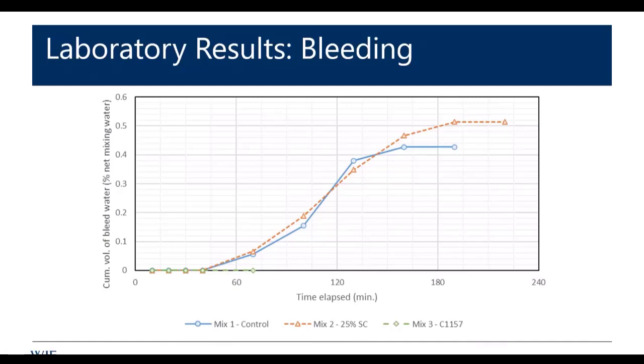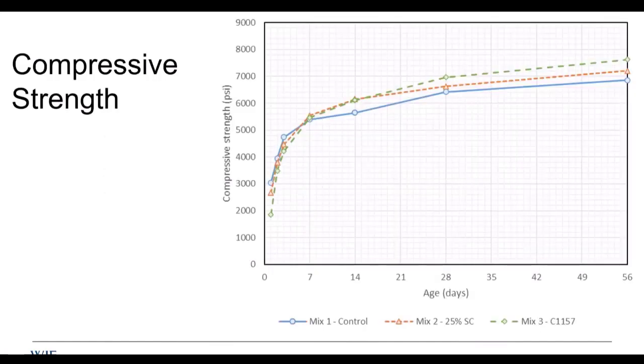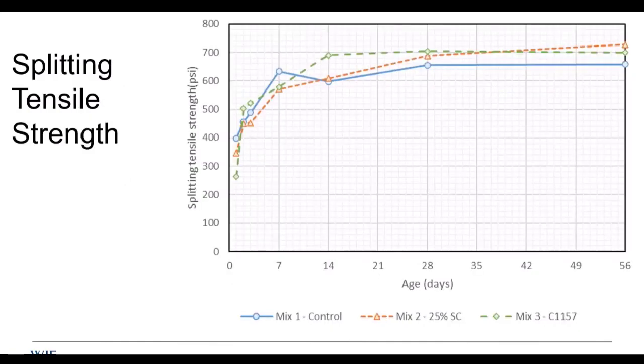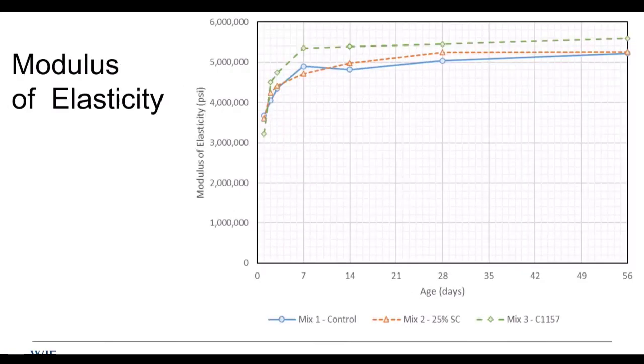Yeah, but so our mix 3 had no bleed. So we got a 9-inch slump with no bleed in the lab. Compressive strengths, very similar. Mix 3 started a little slower in the lab, but ultimately hit a little bit higher. Splitting tensile, hard to differentiate. Modulus of elasticity, a little bit stiffer.